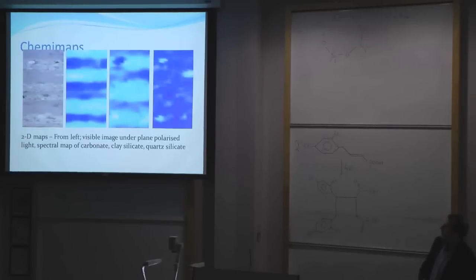And the obvious implication here is that alternate layers on this slide are made from clays, and from carbonate-containing lime plasters. We think that effectively what they were doing was they put a layer of clay, which is quite cheap, on their wall, to cover up all the smoke and the soot and so on, and then a layer of this lime plaster, which was a very brilliant white colour. But we know that they had to go some distance from their site to get this, about 6 kilometres or so. So it's probably quite valuable stuff. And we know that because we've been able to match the chemistry to different sources of material. So this was probably quite valuable stuff, and it made their houses look nice.